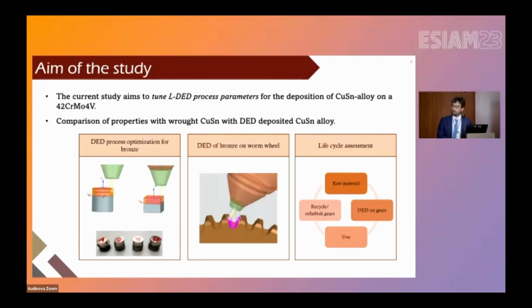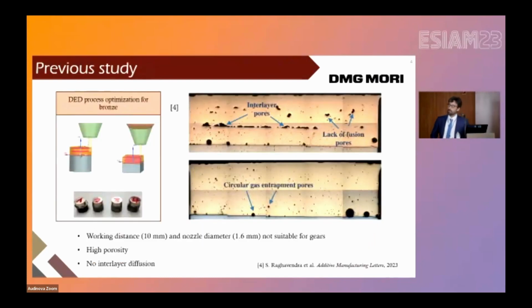So we started analyzing this possible solution. As you can see here, we deposited bronze on small discs of steel. The preliminary analyses are shown here. They demonstrated the possibility of depositing bronze on a steel substrate. These preliminary results have recently been published in this journal paper. But in the end, we realized that there are still some shortcomings that must be overcome.